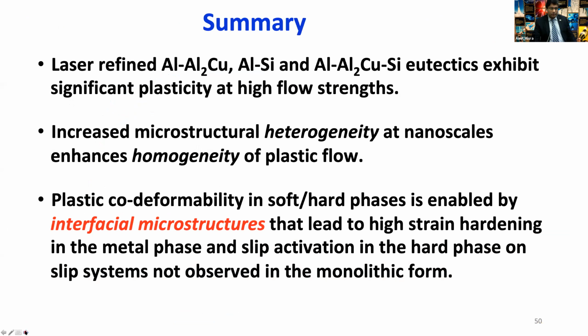So this brings me to the summary of this part to show that these kinds of laser refined structures have been known in the literature to have fine scale structures by laser melting. What is new is that by doing these nanomechanical tests, and especially doing in situ, we are able to see that the increased microstructural heterogeneity at nanoscale enhances the homogeneity of plastic flow while maintaining the very high strength.